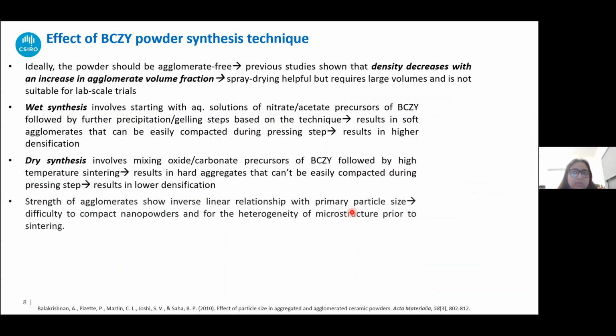Now, ideally the BCZY powder that is synthesized should be agglomerate free, because studies have shown that with an increase in the agglomerate volume fraction, the density also sharply decreases, which is not quite what we want, because that then negates the effect of adding the sintering aid and everything. Ideally, spray drying is a helpful technique that helps in getting rid of those agglomerates. However, for bench scale or lab scale studies, this is not very cost effective.